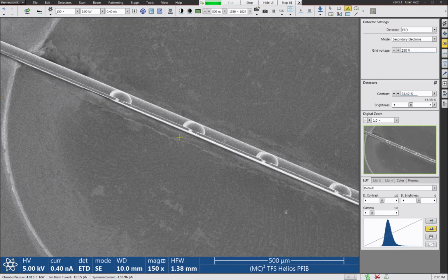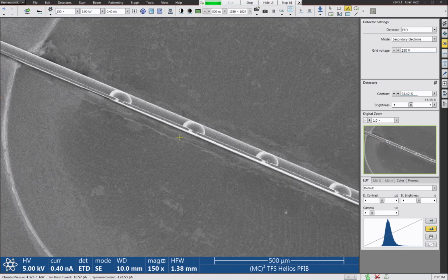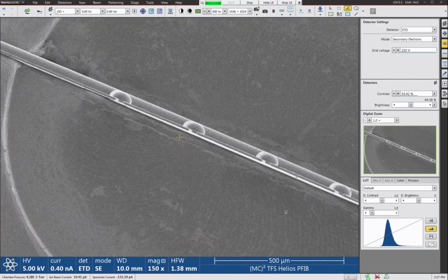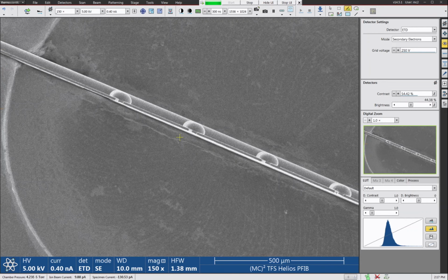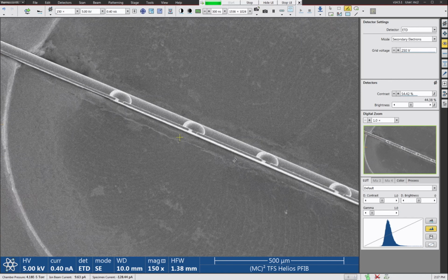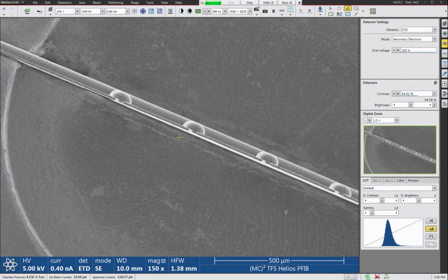They are too close together. When you run these in the atom probe, you're likely to blow up the neighboring posts. And in fact, the safest thing I think is to actually just sharpen the outside two fingers on each grid. So each grid will have two posts. I've got two grids in here. That would be four posts total.